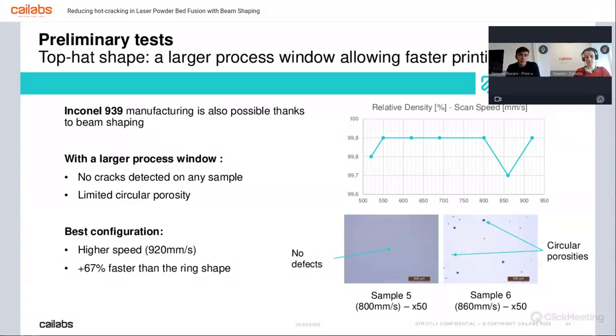Following the ring shaper, we go to the top hat, where we have way better results. In particular, we have tried the same parameters as for the ring shaper, and we have tried different scan speeds. This time we have observed no cracks in any sample for any different scan speed and very low porosity. That is just circular. That, let me say, is the least dangerous defect for additive, because you are not introducing any edges that can increase the stress concentration. And in particular, the lowest one was 99.7% density of the material.